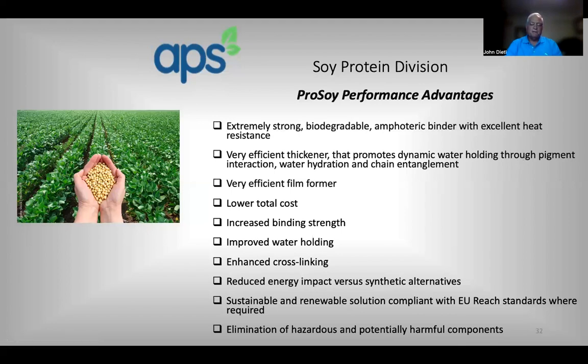If you put us into an ink formulation, you can take out a product that is made from petroleum base, put in a more sustainable, a more environmentally friendly product that will give you the thickening and will also keep you from getting blisters when you go through the drying process on a real fast offset web press. And we go smoking through there and start drying the printing ink real fast, and all of a sudden it starts popping. That's typically what'll happen with something that releases water too fast. In addition to that, after you cut the board and it stacks on top of one another, it prevents scuffing of that ink on the board. And that's why a lot of our customers will use it in that type of environment.